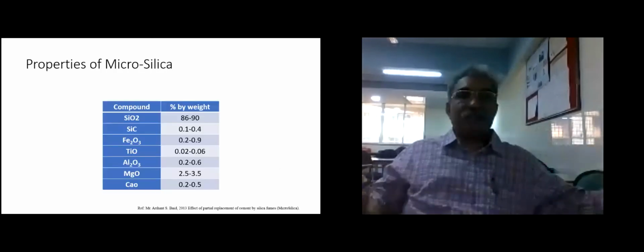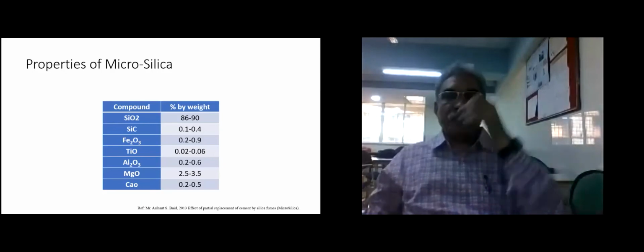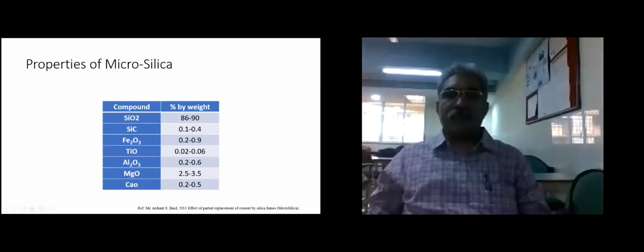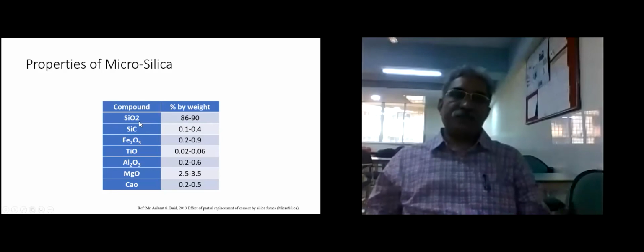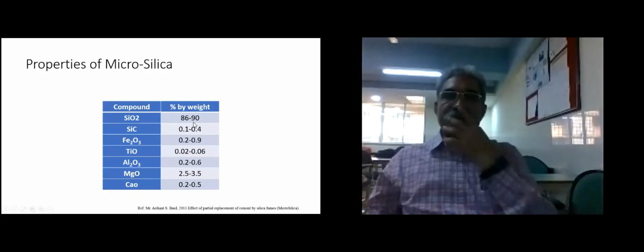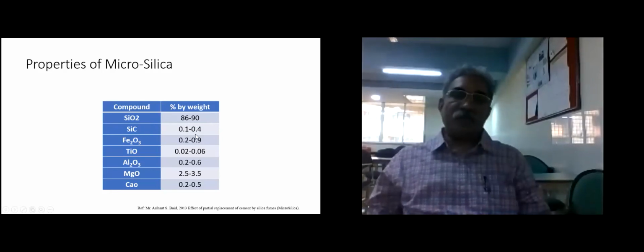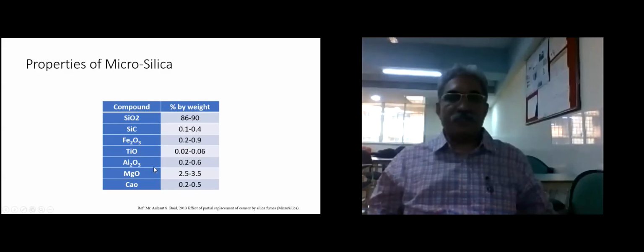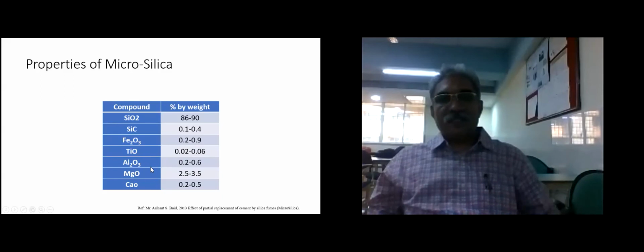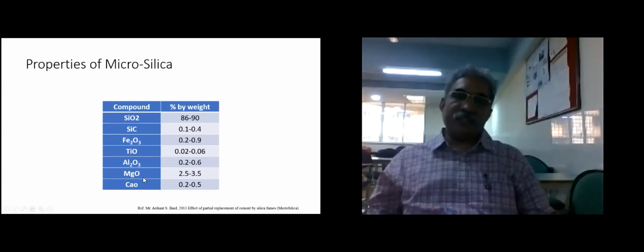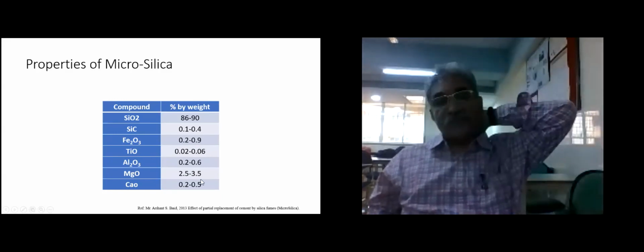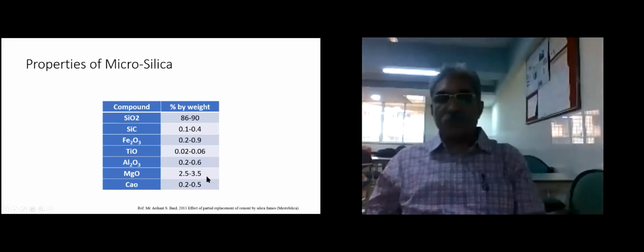Properties of microsilica: the compound and the percent by weight. SiO2 is 86 to 90, SiC is 0.1 to 0.4, Fe2O3 is 0.2 to 0.9, TiO2 is 0.02 to 0.06, Al2O3 0.2 to 0.6, MgO 2.5 to 3.5, CaO is 0.2 to 0.5.